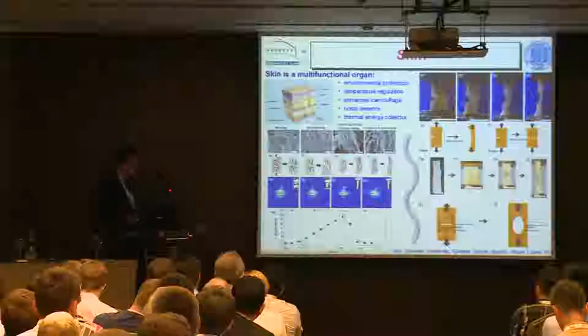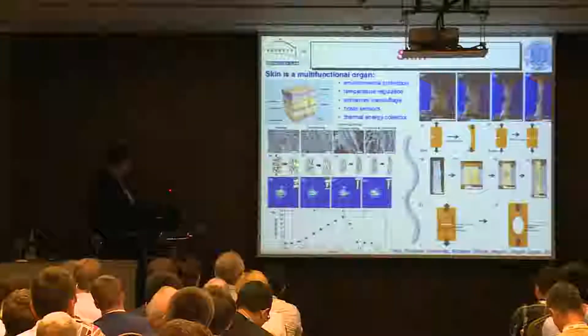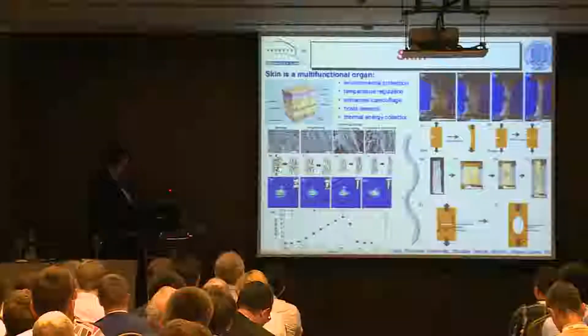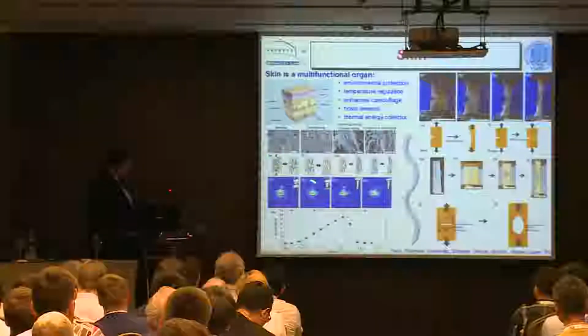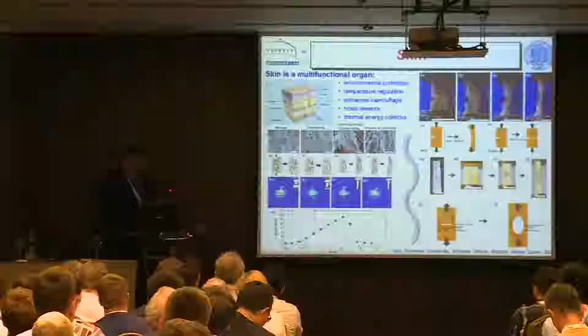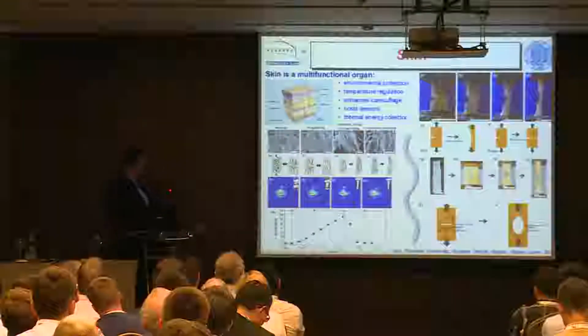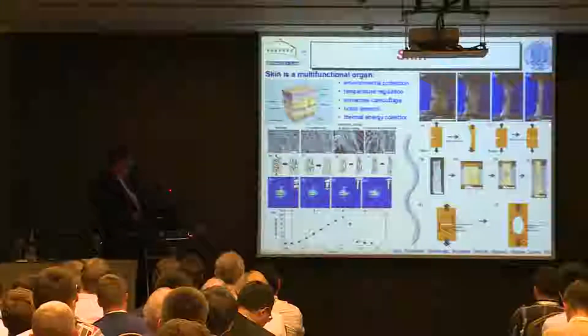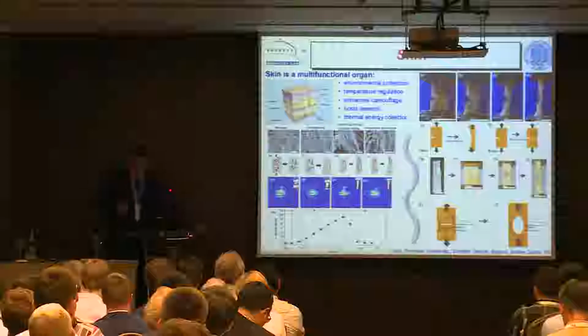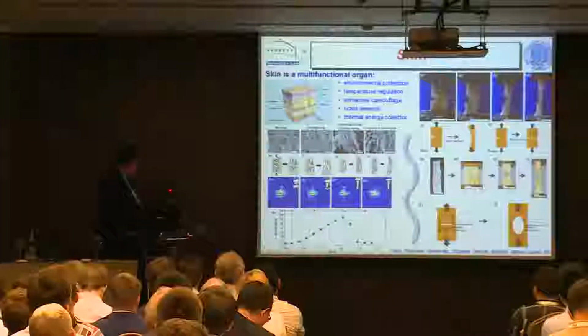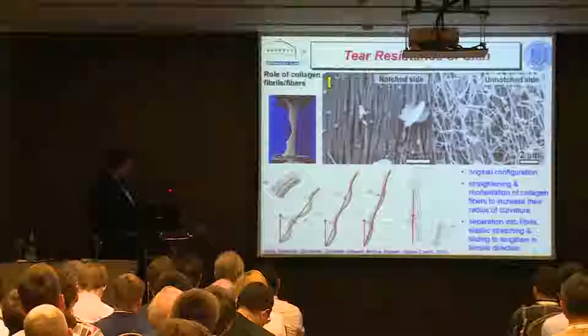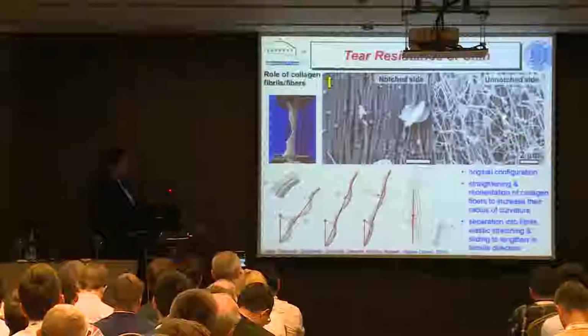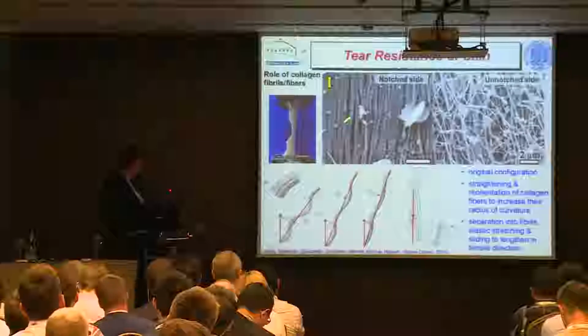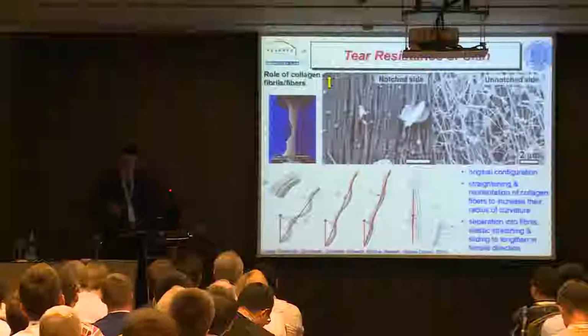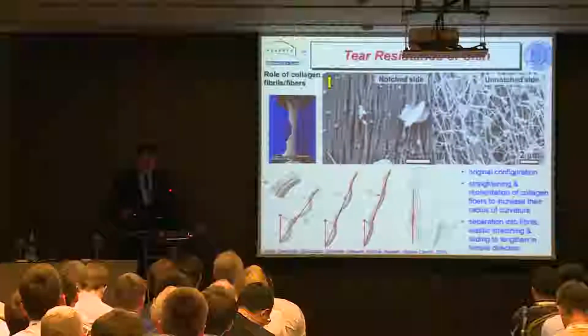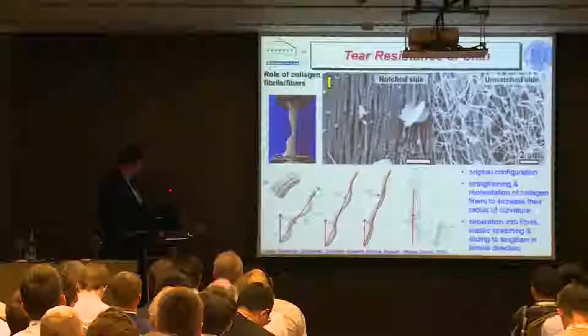You get a series of processes. The collagen is sort of a bit of a mess to begin with. It's all tangled. And as you start to pull it, it will first of all start to rotate. It then starts to straighten. It uncoils here. It'll then sort of stretch apart. And then finally, if you pull long enough, it'll break. And we can watch this in real time. Just to make a long story short, these are sort of images. The collagen in skin looks like this to begin with, and when you've really broken it, it's fully aligned like this. So these are very effective mechanisms for absorbing energy and increasing the tear resistance.